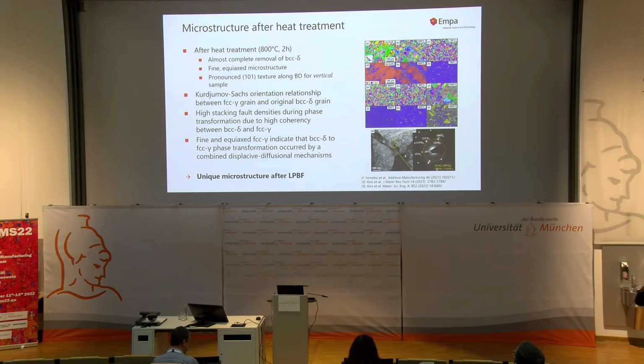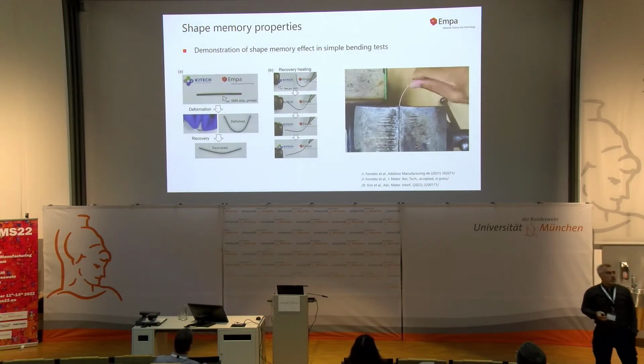Interesting, with regard to the shape memory effect, we'll come back to that later, we also see very high stacking fault densities that we create during the phase transformation. And fine and equiaxed FCC gamma indicates that the BCC delta to FCC phase transformation occurred by a combined displacive-diffusive mechanism. So all in all, in comparison with conventionally manufactured material, this microstructure is fairly unique and also explains our behavior later on.